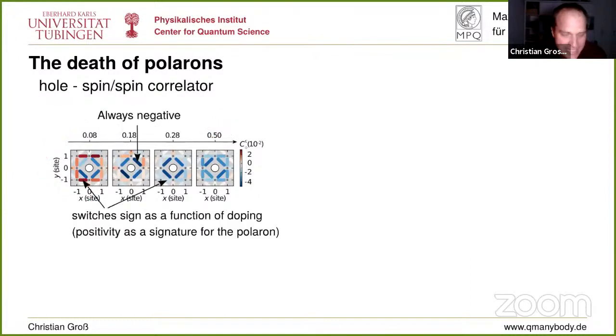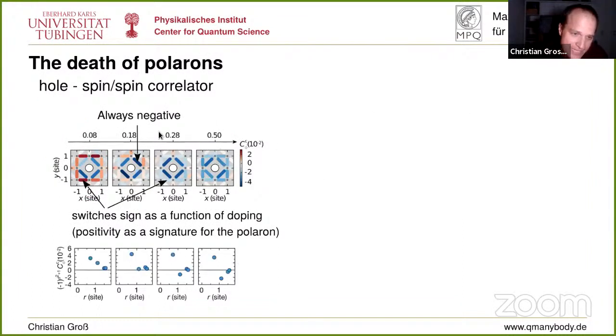And if we basically use that information and make that clearer, we can make a graph that shows the strength of these spin correlators for different distance, right? This is again the middle of the correlator, which is the distance that is given here. And it's constructed such that it is positive when the spin correlation that we measure is opposite to what you expect for a standard fully filled antiferromagnet. And then what you see is basically that in the low doping, we see everything flips. This is this polaron signature, right? It really messes up the spins. But when we increase the doping, we see basically that polaron signature goes away. And the only thing that survives is this very nearest neighbor point. But the signature further away really dies.